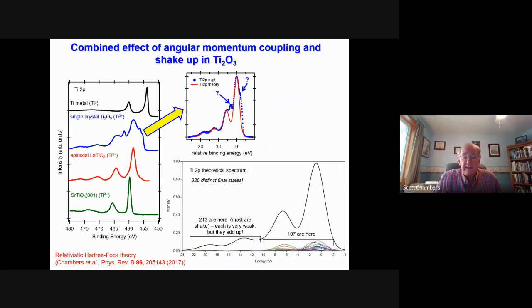And what happens here is that conduction band electrons screen the core hole and stabilize it in that particular atom, so they come in at a lower binding energy. The reason we didn't get it with these calculations is because Paul used an embedded atom approach, where he had one quantum mechanical cluster, a TiO6 cluster, shown there in the middle, and blue is the titanium. And then he had a bunch of other ions at the appropriate places in the lattice, but they were treated classically. If you only have one metal atom being treated quantum mechanically, you can't have a conduction band. And therefore, there's no conduction band to screen the core hole. And that's why we didn't get these in the calculation.